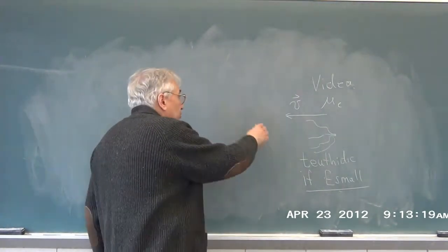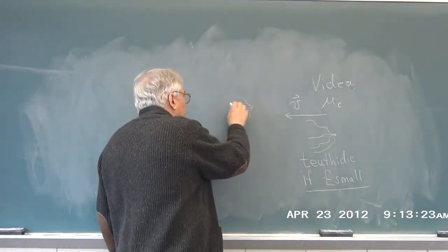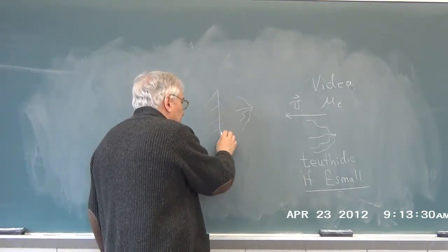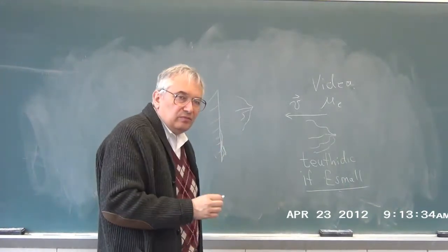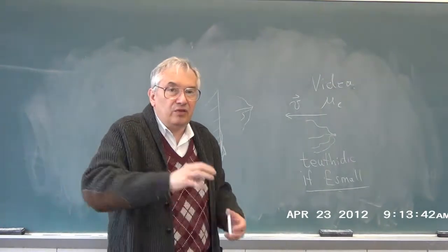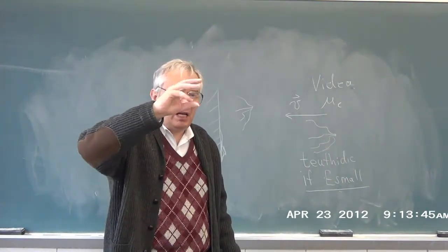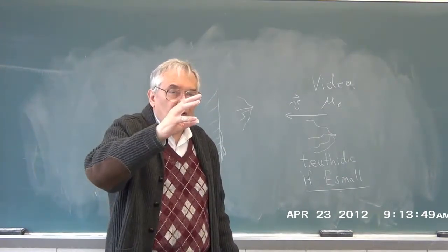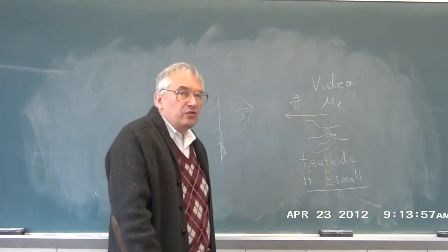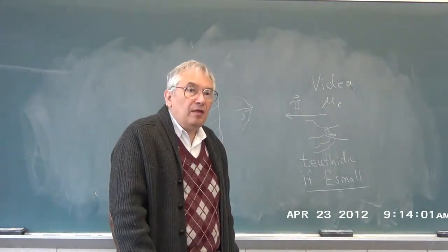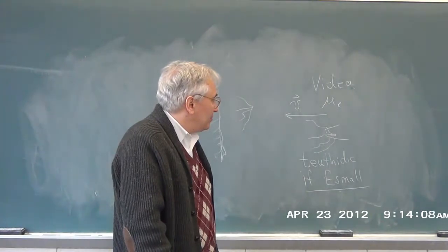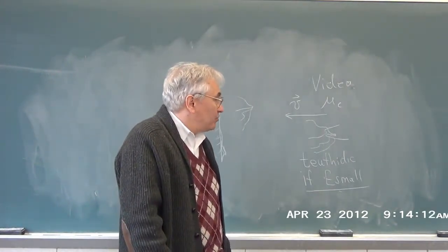And I should stress this is solutions, not melts. If you have a star chain diffusing through a solution, and here is a cross-linked gel, when the star comes up to the gel, it can't penetrate, it just flattens out on the surface. Well, if that's correct, then star polymers diffuse through solution via teuthidic motion. The arms move, the body is dragged behind. If there are other entrained polymer coils, then it must be the case that the chains are being dragged along.